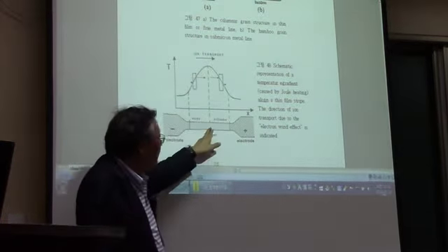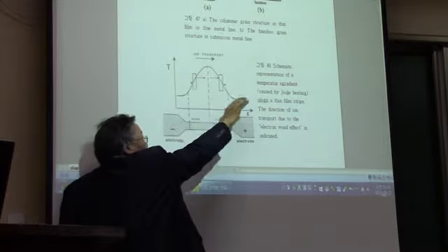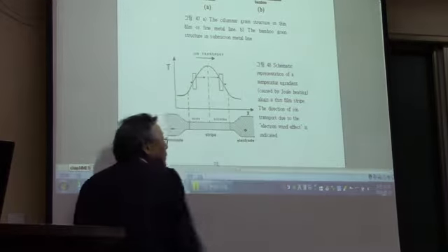So relatively you have a lower temperature at both ends, and at the center you're going to have a high temperature. Then you are going to have a temperature gradient like this, and at this slope of temperature, more ions are going to move toward the high temperature, but at this slope, fewer ions are going to move towards this end.